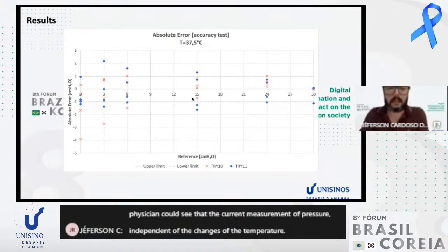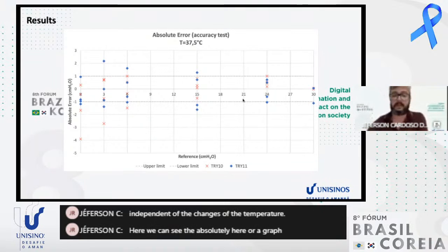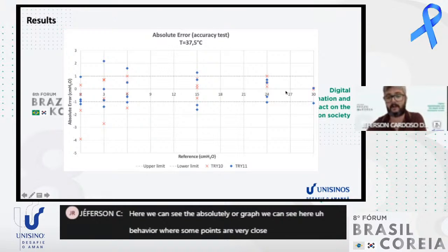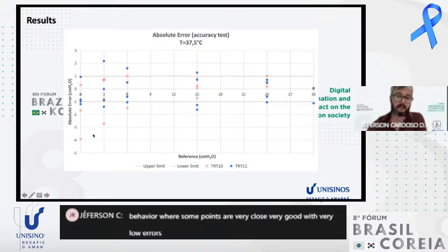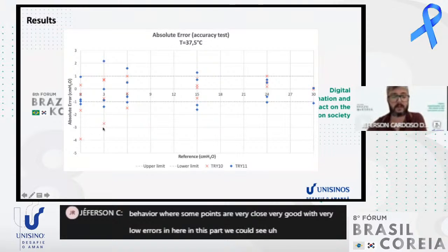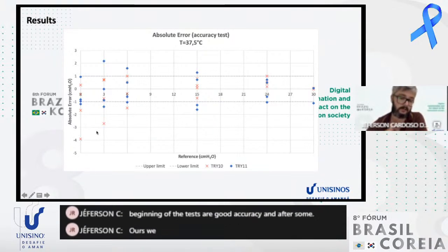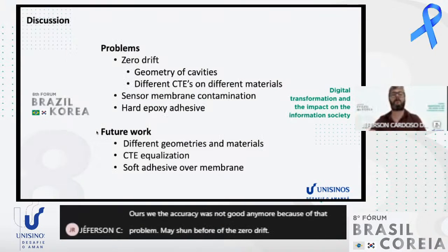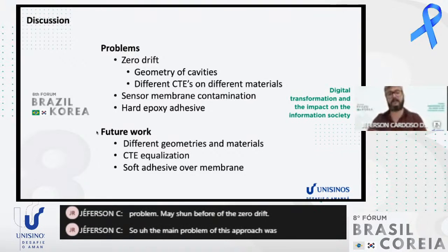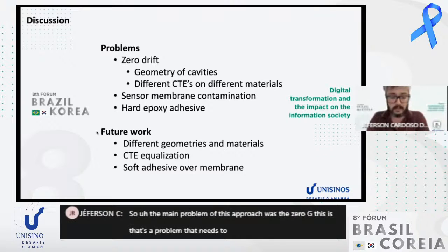Here we can see the absolute error graph. We can see here behavior where some points are very close, with very low errors. And in this part, we could see bigger errors. That's because of the protocol of the data collection, because of the problem of the zero drift. So we can see in the beginning of the test a good accuracy. And after some hours, the accuracy was not good anymore because of that problem mentioned before, the zero drift. So the main problem of this approach was the zero drift. That's a problem that needs to be fixed.